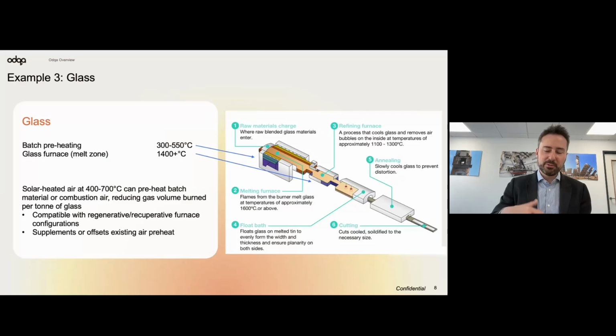The third example that I wanted to touch on was glass. This is another incredibly high temperature process, 1,400 degrees. This would actually be similar to many metals. You can imagine melting steel, melting aluminium is also an incredibly high temperature process. Typically, there will be preheating. You don't want to create a thermal shock for your product by going straight to these high temperatures. There's also waste heat recovery from the furnace that comes into the preheating stage.